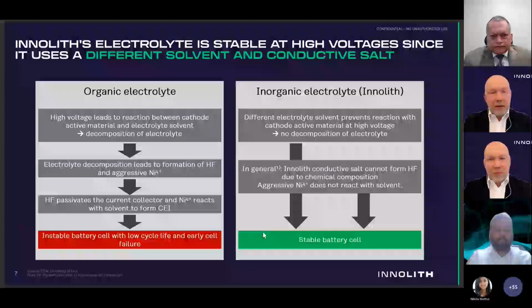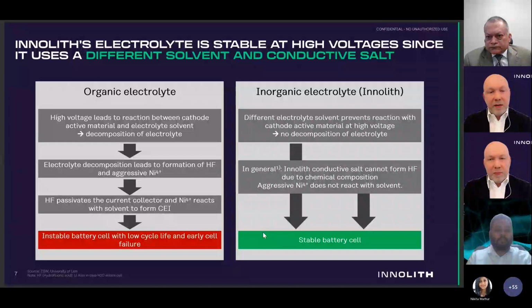On the left side, you can see what happens with conventional organic electrolyte when it's cycled to high voltages. And I would remind you that high voltages are required in order to get access to more of the available lithium on the cathode side. A high voltage cathode in conventional electrolyte reacts with it, oxygen is released, and it leads to decomposition of the electrolyte and formation of very toxic acid, HF.